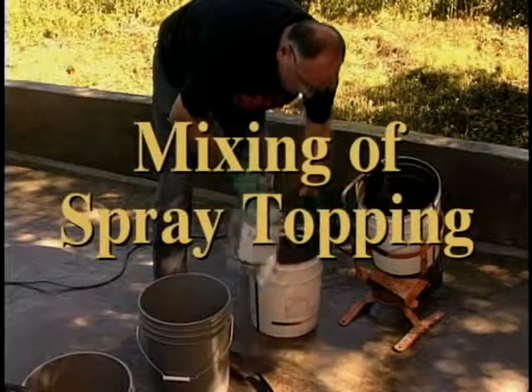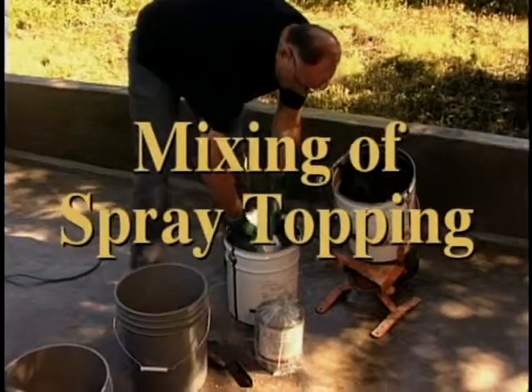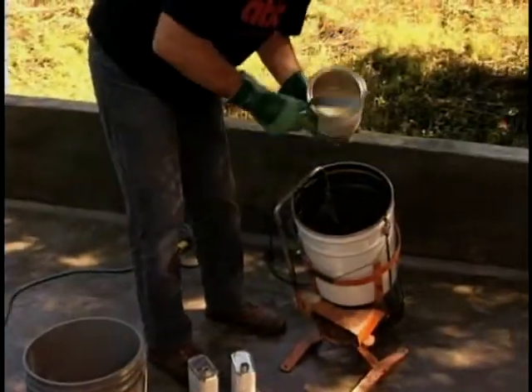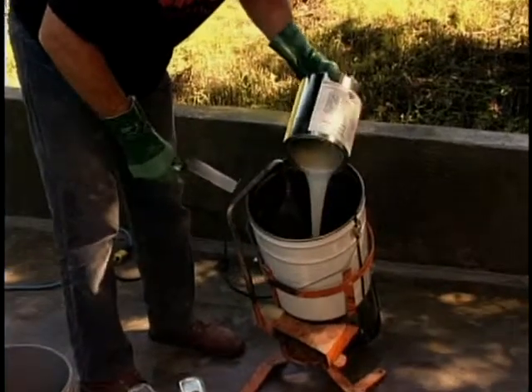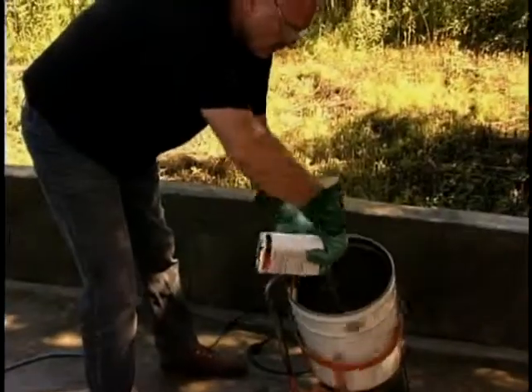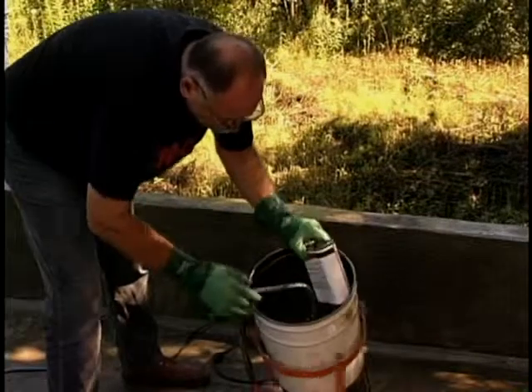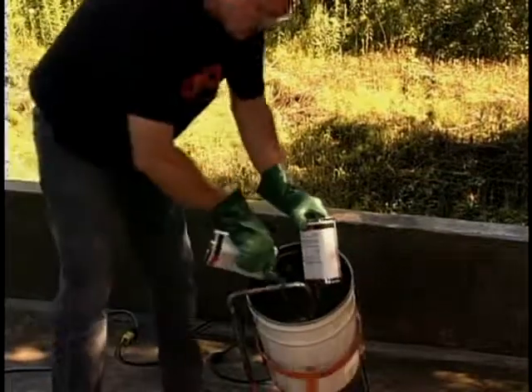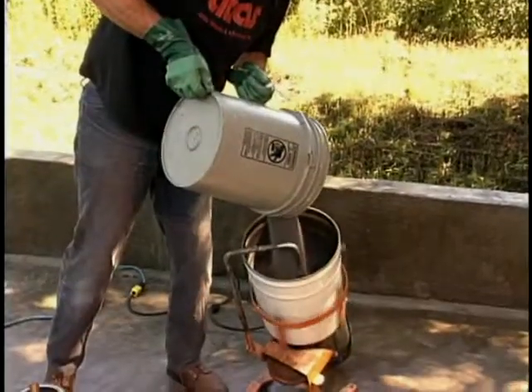Remove the powder and the resin in the hardener cans from the pre-packaged unit. Pour the resin into a 5-gallon mixing pail. Scrape the sides to remove all the material and begin mixing. Add the hardener and mix for 2 minutes. Add the powder and mix until uniform.